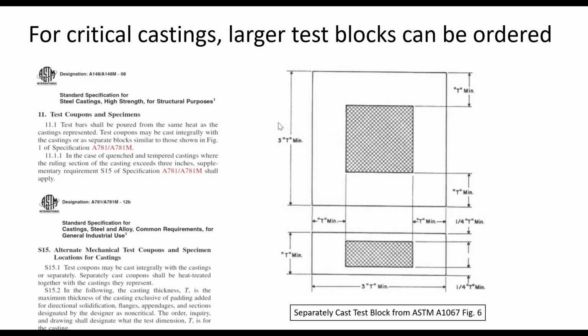Now, if you are making critical castings, things for the oil field, things for the Navy, then people want larger test blocks so that you can actually directly correlate. And so actually in ASTM A148, that is a specification that lets you order steels by properties, not alloy, and the foundry or the producer gets to decide what alloy to make. And so in this specification, it says if you're going to have a quenched and tempered steel casting and it's thicker than 3 inches, then you've got to meet the requirements with S15.